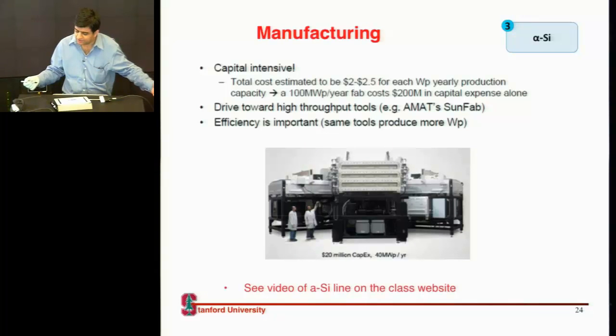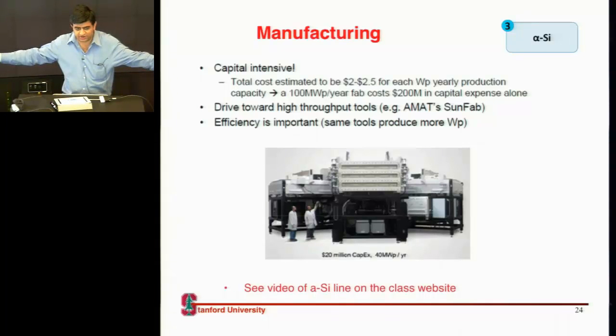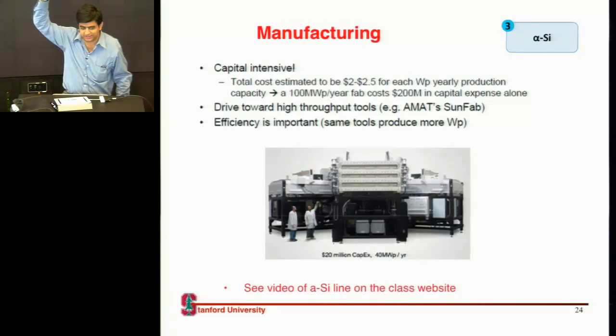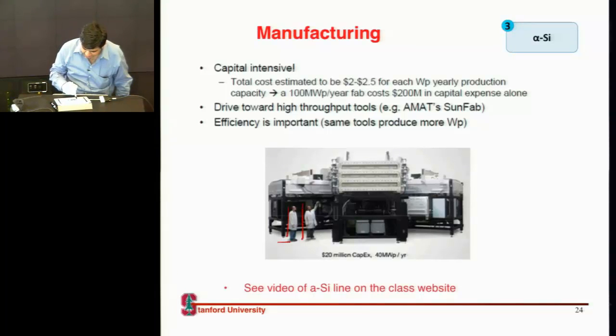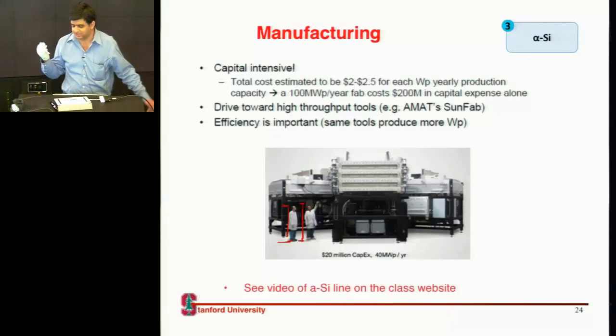And the only way to scale this process is to use these large panels of glass. I remember we used to sell a line which did process on glass which was 5.6 meters square, and that's much taller than me. And there would be these chambers, so just to depict the might of these chambers, these are two people who are standing next to it. This chamber is big enough that I've been in one of these, you can stand inside one of these, and you can have a barbecue party inside. It's that big of a chamber, and you have 6 of them or multiple of them connected in a cluster.